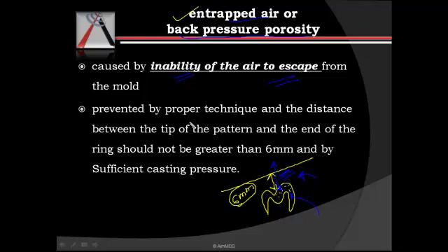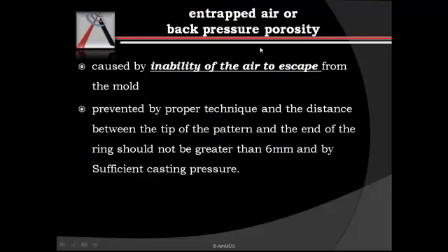Right? So this can be prevented by proper technique, and the distance between the tip of the pattern and the end of the ring should not be greater than 6 mm, as we already saw. Further, sufficient casting pressure may help to drive out the gas. So that is one more way to prevent the entrapped air or back pressure porosity.